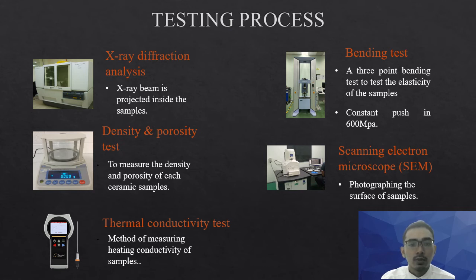Next is the thermal conductivity test. It is a method of measuring the heat conductivity of a sample. Two ceramic samples are put together and a probe is used to stick between the samples while the sample is heated for a period of time. Next will be the bending test. A 3-point bending test to test the elasticity of the samples. Based on the 3-point, a constant push of 600 megapascal is used to test the elasticity of the sample.